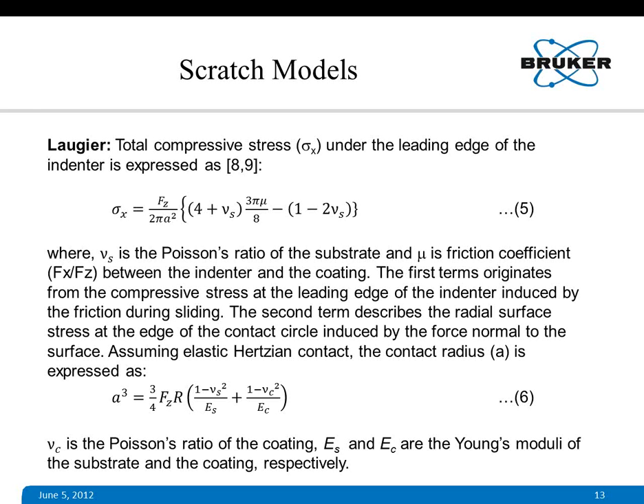substrate system. Of course, it is not fully proved, but in most of the cases it has been found and people have worked on this. So Laugier tried to correlate this, tried to incorporate friction in this model. Assuming elastic Hertzian contact, the contact radius A is expressed in equation 6 by Laugier. And using equation 5 and 6, we can calculate the critical shear stress of the coating. That is adhesion stress basically.